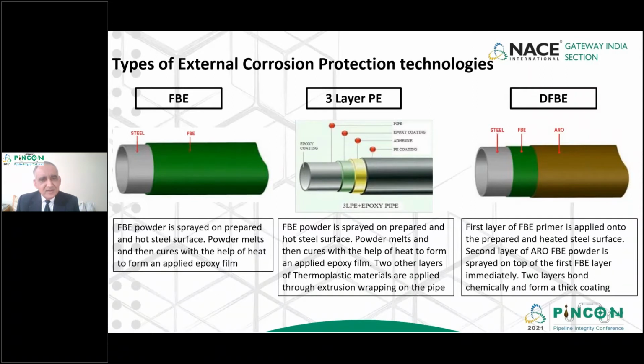And so there are some impacts and some damages noticed in the case of single layer FBE coated pipes. So the industry came up with a very robust design of three-layer system. That means the first layer is still FBE, which provides corrosion protection. Then there are two other layers. Adhesive is one, which attaches the FBE layer and the outer layer of polyethylene compound. And it's all applied through an extrusion process.